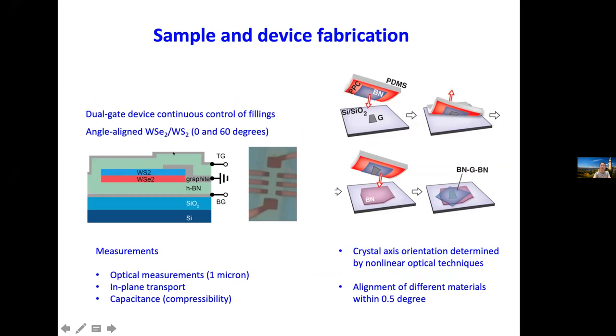And this is a typical device. We have the moiré system encapsulated by HBN and very thin graphite gates, which light can penetrate through. So for optical measurements, we have spatial resolution on the order of about 1 micron, and you can also do transport or capacitance measurement at the same time.